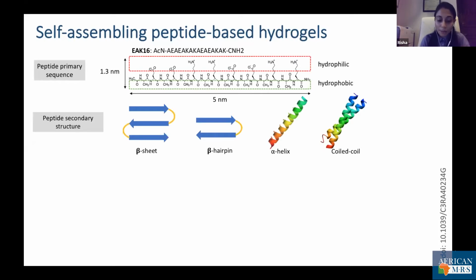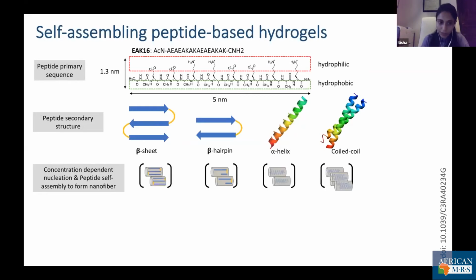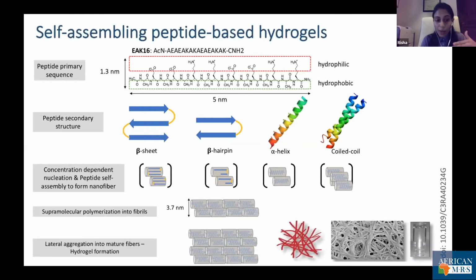Now, the general mechanism for this hydrogel synthesis is a concentration-dependent nucleation followed by fiber elongation, so that it forms long fibrils, and then a lateral aggregation to form these mature fibers. So these are interesting hydrogels, which we can investigate further, which are being investigated in our lab as well.